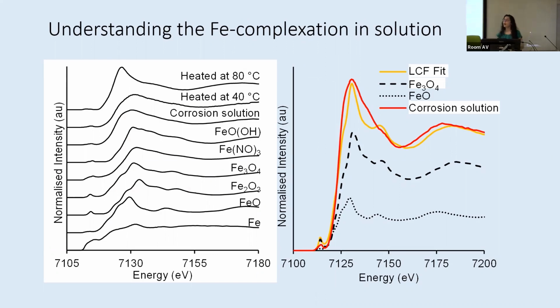And I think this is where I like to blend the fundamental scientific approach with an industrial problem. Because the reality is that traditionally there are a range of inhibitors that you might apply in your system. You might apply them in solution, you might add a coating, but you do something to stop effectively that oxidation from happening. The problem is that that's not necessarily a well-informed decision in all cases, because we don't necessarily understand exactly the problem we're treating, and we don't really know if the treatment is actually appropriate.